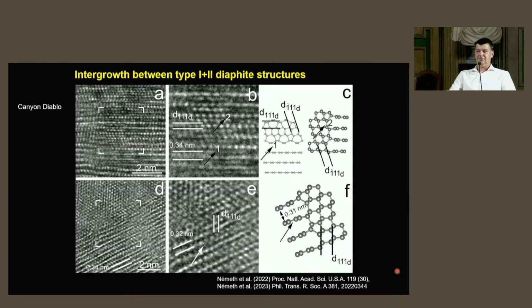Now, even the different type 1 and type 2 diaphite structures could intergrow with each other. So a type 1 diaphite structure, we found that it extends, it continues into the orthogonal projection of type 2 diaphite. Or we found even the type 1 diaphite occurs on top of type 2 diaphite, which gives rise to complex HRTEM images.